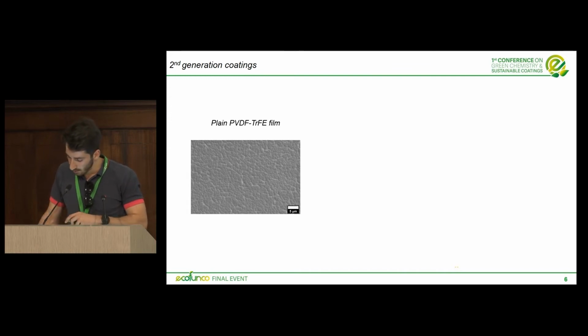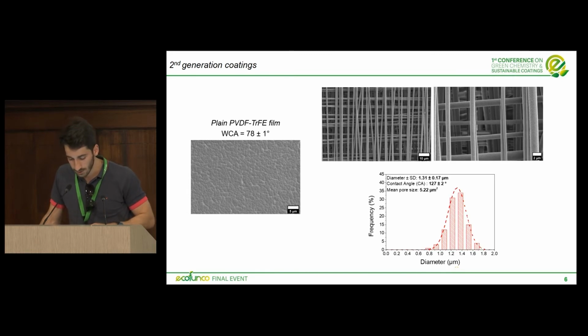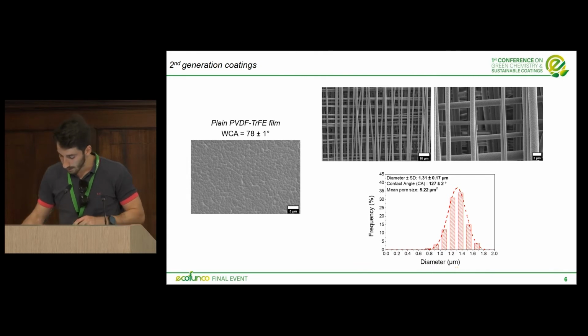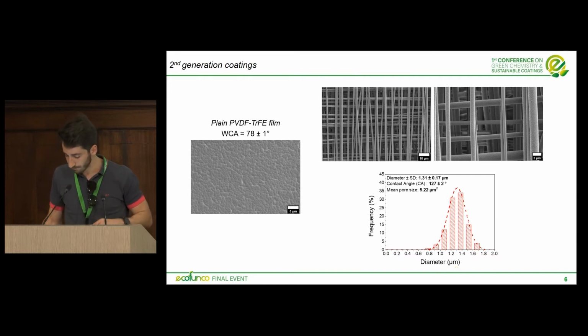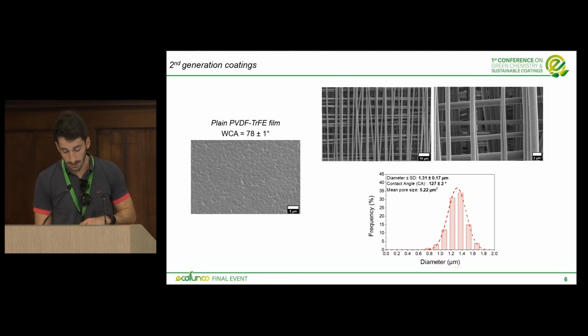In this way, the fibers were more anchored, and we were able to produce coatings up to 10 layers of aligned fibers. Here I reported the water contact angle of the plain PVDF-TrFE film, in view of then correlating this water contact angle with the contact angle of the coating. And we can see that the fibers had a larger diameter with respect to the first generation coating, and in this way we produced a super-hydrophobic coating with a contact angle of 127 degrees.